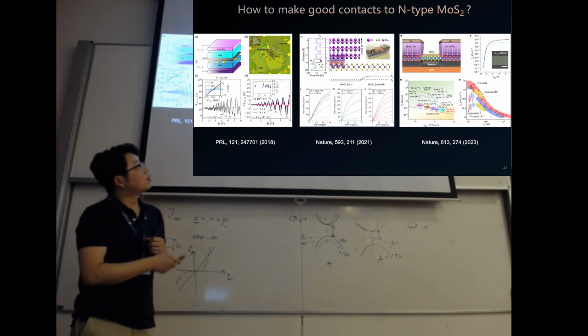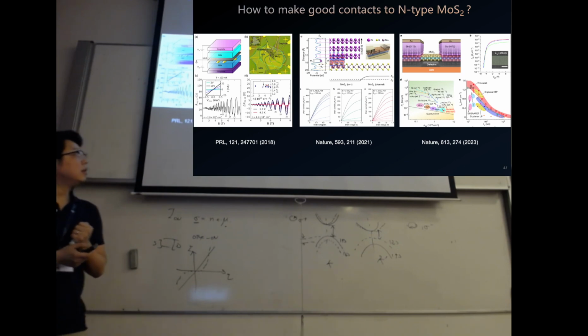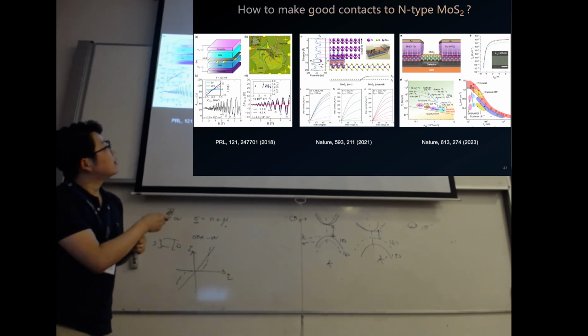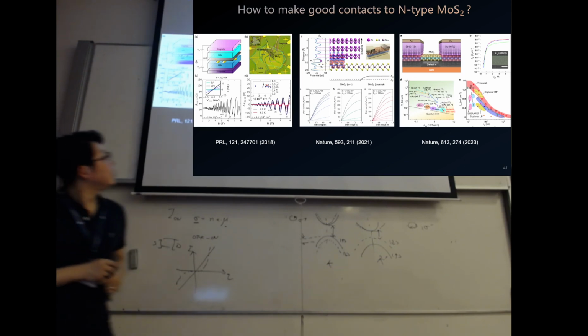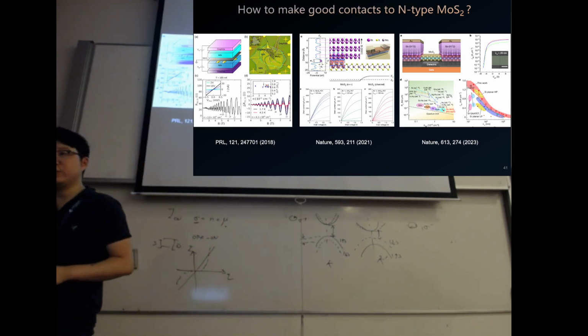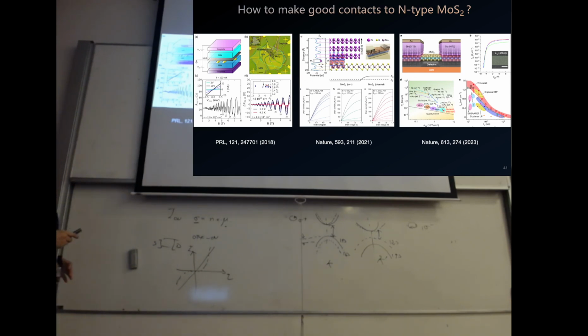And later on in 2023, there's another paper coming from Nanjing University, China. They found that using another material, antimony, and specifically the (01-12) surface, I don't know if they found it accidentally or predicted something from theory and then started experiments. Anyway, at the end, the (01-12) surface of antimony can have a very good contact to MoS2, and they give the contact resistance as low as the quantum limit, about 40 ohm micrometers. So these are the two ways found in literature towards a very good contact to MoS2 at room temperature.